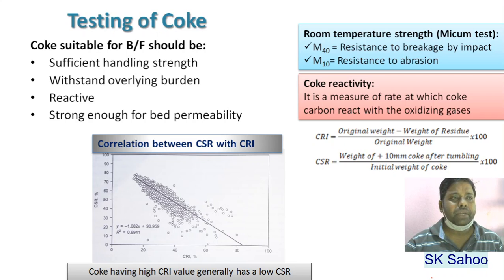Coke suitable for blast furnace should be sufficiently strong to resist shatter during the handling prior to charging. That means during the charging and raw material handling, it should have much higher strength so that fine generation will be less. It should be able to withstand the pressure exerted by the overlying burden. Because the blast furnace is huge and tall, so much burden is there, so coke has to withstand all the burden because it is the solid material till the tuyere level before burning.